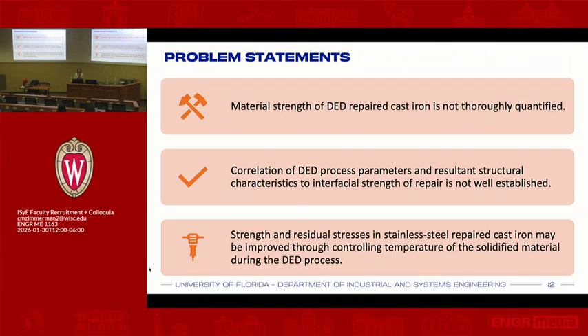Like I mentioned, with repairs, the difficulty is that you have an uncontrollable initial setting. So to have those parameters completely correlated is a little bit difficult, and you have to be almost on the fly. And the other important aspect, if you're using stainless steel, is that it's very difficult to control temperatures associated with the bonding between those two materials. So those are the problems, and we're going to have so much uncertainty. So what can we actually do?